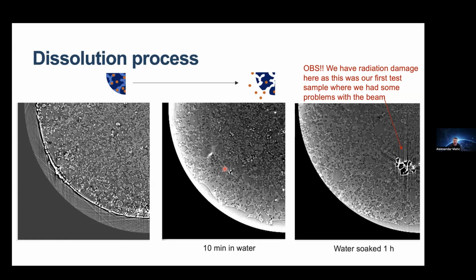So now we are on the way to do a lot of image analysis to quantify these changes. This is also an important part of the experiment, the analysis, where you have to work a lot with your images. You collect quite a lot of data. It's important also to highlight another thing when doing X-ray experiments on soft materials, as wood-based materials are: you can sometimes have quite large effects of beam damage. And to the right here, you can see an example that after 1 hour of measurement, we could see things which probably should not be there, that we have beam-induced effects.